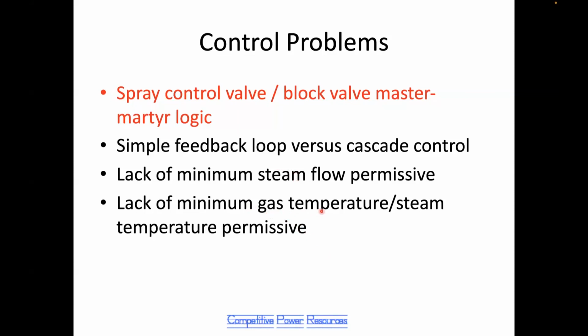A minimum exhaust gas or steam temperature permissive should be in place so that the block valve cannot open until the steam temperature and gas temperature driving that steam temperature are high enough. On a large HRSG, F-class HRSG, it'd be somewhere around 500 degrees C. If gas temperature is below that, you should not allow the Attemperator to open at all.